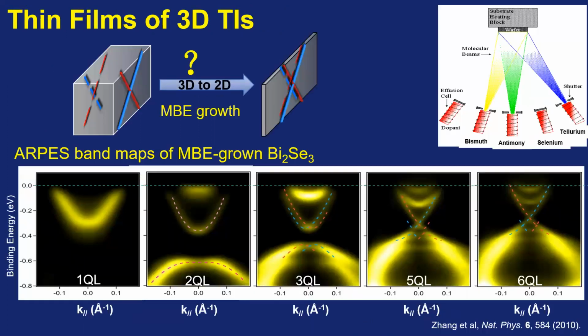So next, I will show you how to realize the quantum anomalous Hall effect in the experiment, step by step. The first step is how can we get the thin film of topological insulator? Our approach is MBE. We use MBE to grow the 3D topological insulator bismuth selenide family material. This is the bismuth selenide film growing on the graphene substrate.